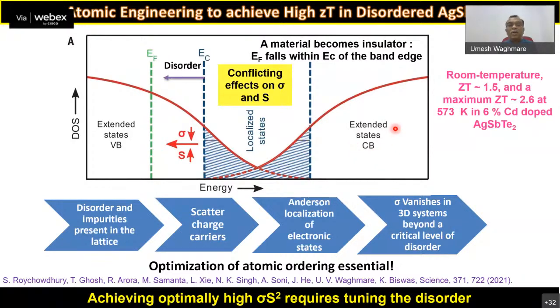So what our experimental collaborator Kanishka proposed is that we can engineer the disorder. That's why it's called atomic engineering of a material. Here is AgSbTe2, silver antimony telluride. It's a single crystal, where silver and antimony are randomly distributed at the same lattice site, and that causes the disorder. It's called anti-site disorder, and that gives you this localization. So achieving optimally high disorder, which will maintain semiconductor character as well as high conductivity, is what we achieve.